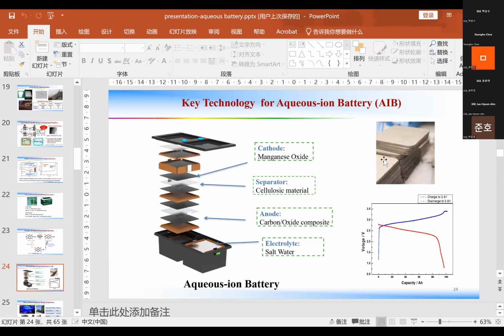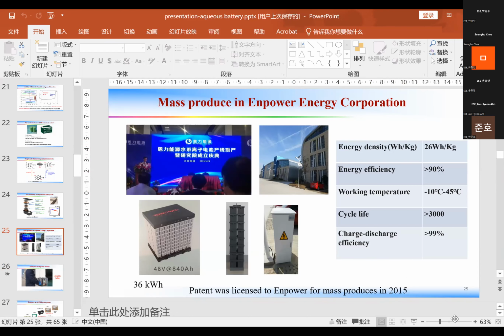But we must, because for aqueous lithium the open voltage is very low, around 1.5 volts. Normally we must prepare thick electrodes. Then in 2005 we had a patent. This uses a spinel as the positive electrode, and it contains activated carbon and lithium titanium phosphate. And this patent was licensed to Enpower in 2015.